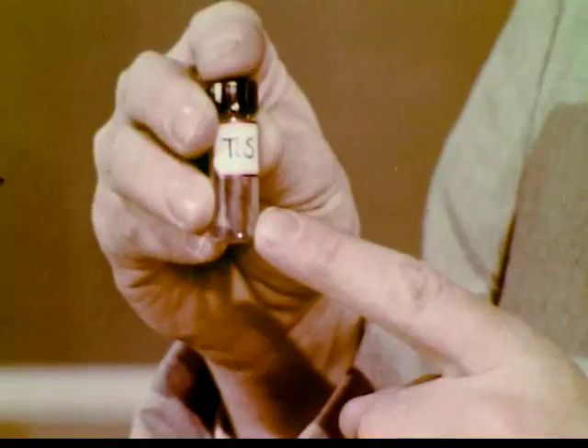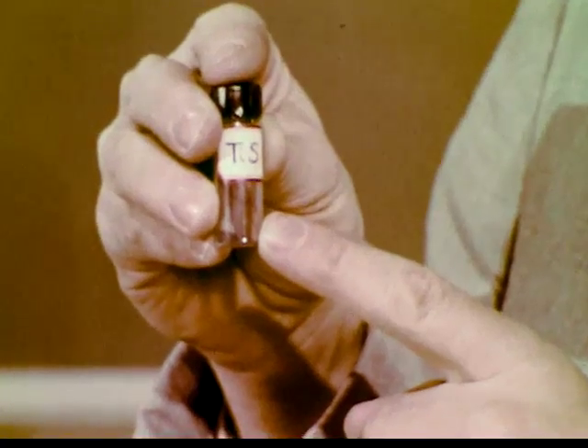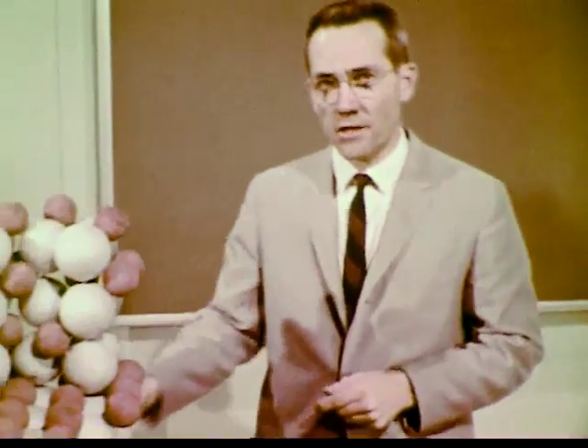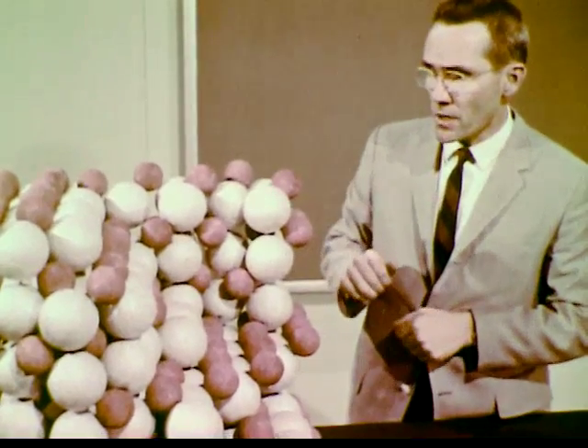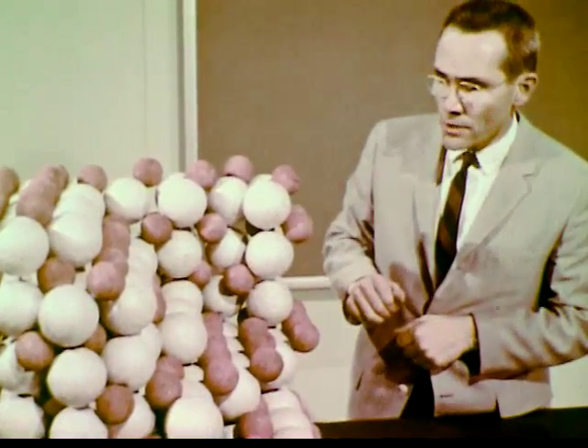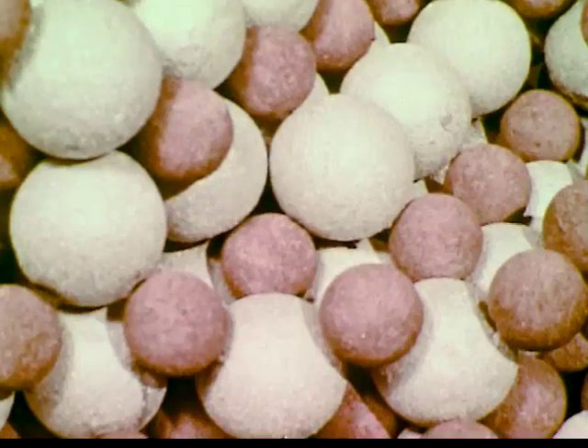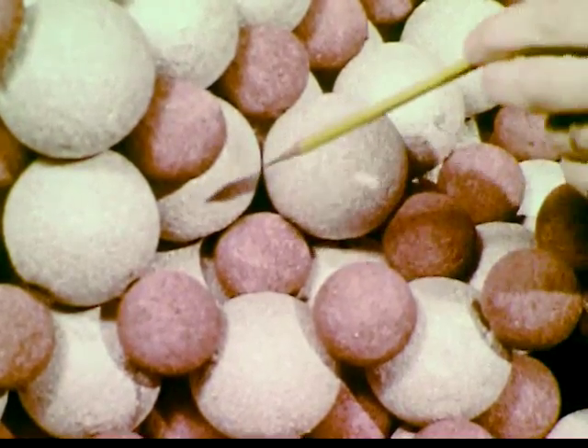Here is a high melting substance on which Dr. Hugo Franzen and I are working. It is titanium monosulfide. It is prepared by heating together powdered titanium and powdered sulfur. Its structure, as obtained from X-ray diffraction studies, is shown by this model. The red ones show the position of the sulfur atoms, and the silver ones show the position of the titanium atoms.